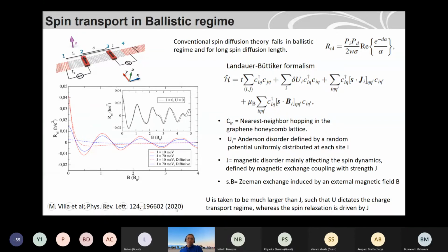So in this paper, which was last year, it has been developed how the spin transport in this ballistic regime will look like. You can look at this paper for details. It's a quite nice paper to understand. So you can take this Landauer formalism here, and there are different terms as you see. The first one is the nearest neighbor hopping in graphene. And the second term, this delta U, is called the Anderson localization potential. So then it's actually some disorder in the graphene you introduce, because your graphene will never be perfect.